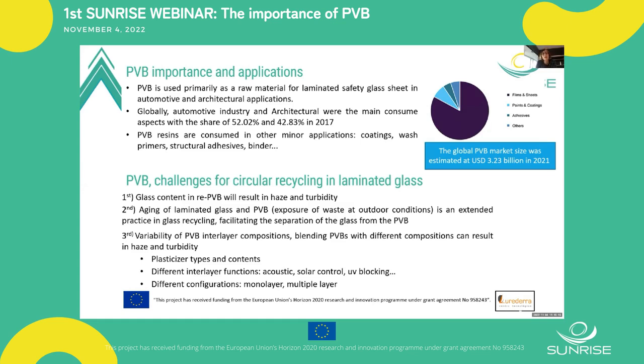On the other hand, we also know from the literature that if we mix different PVBs with different compositions, for example in terms of plasticizers or in terms of contents of hydroxyl compounds, we could have some haze in the final material. Mixing these materials could involve mixing different refractive indices, and this could involve different properties and haze. So this is also an important challenge: try to avoid the mixing of compositions.